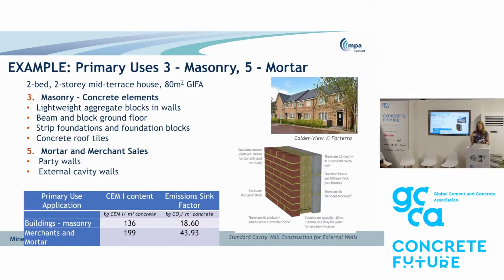And again, we assume that the carbonation front will have passed completely through the full depth of the mortar over the course of the building service life. And in this case, we found the CEM1 content to be 199 kilograms of CEM1 per metre cubed of concrete, and we have that higher emission sink factor of 43.93.